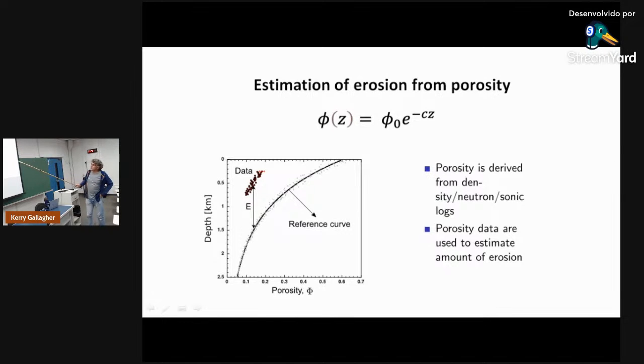So the idea of using porosity, typically we parameterize something like this. It's very simple, that porosity phi as a function of depth is some kind of exponential decay. And that's sort of what you see in the data often. And we have 2 parameters. We have porosity at the surface here, and this constant C tells us how quickly the porosity decreases with depth. Okay. So to simulate that, we need to know these 2 parameters.